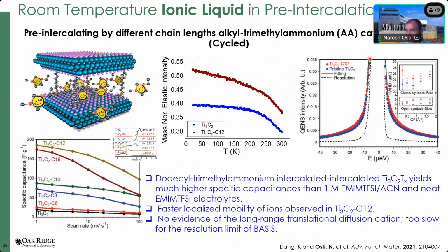We took the quasi-elastic signal, and here it is. As you can see, there is quite a difference in the signal width as well. As before, we extracted the width of that signal and plotted it as a function of Q. We needed a two-component model here. The first component comes from some sort of rotational or caged motion, but there is no long-range translational mobility, so it is Q independent, kind of flat. It means that once the ionic liquid gets in between the layers, it is not showing long-range translational mobility in this particular system. That's what we found.